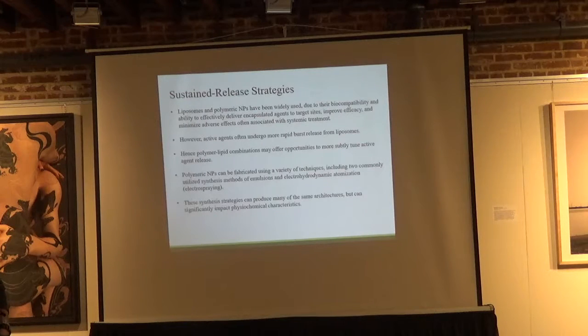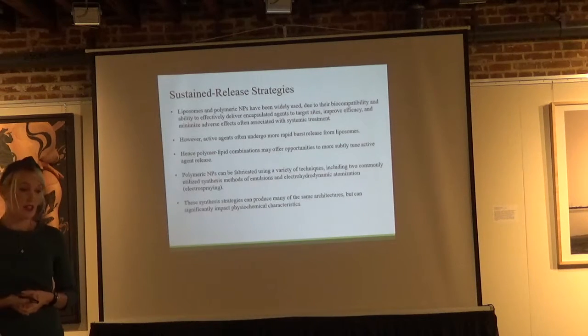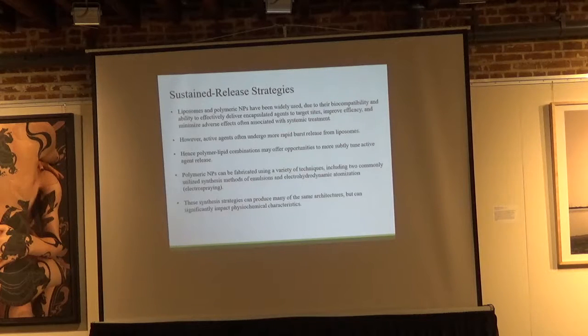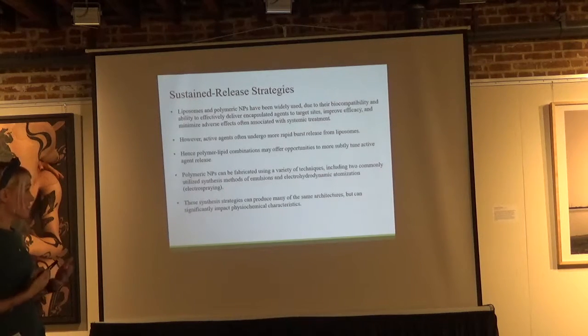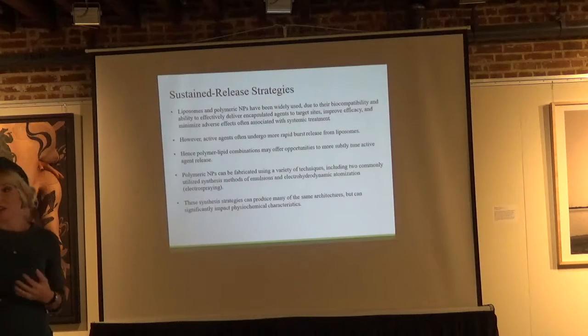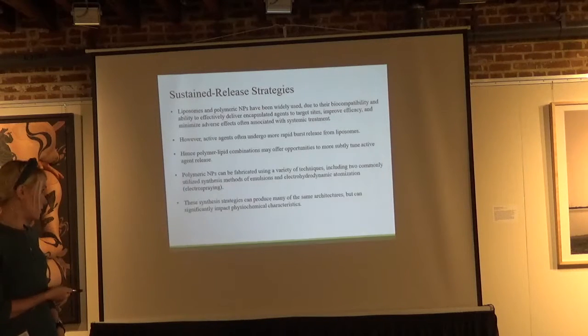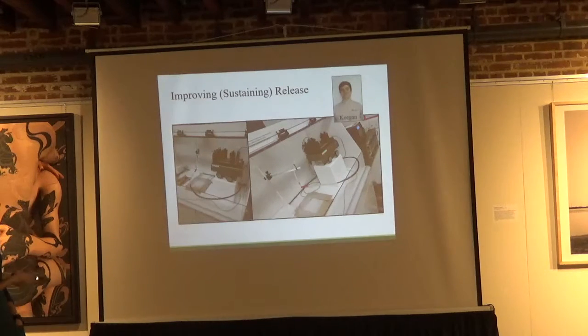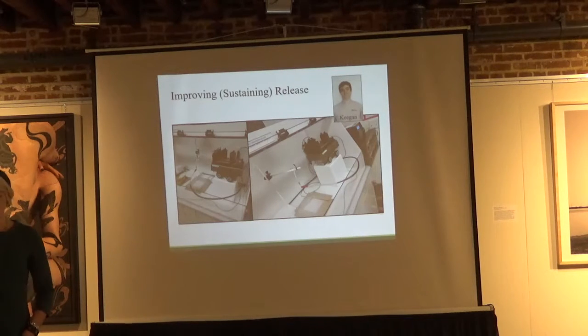However, active agents often undergo, as I showed in those plots, more rapid burst release, and in particular for lipids, it's often even worse. So the thought is that polymer-lipid combinations may offer opportunities to more subtly tune active agent release. And we can fabricate polymeric nanoparticles with a variety of techniques, but the ones that we have going in our lab are emulsion-based and electrohydrodynamic atomization, which is also called electrospraying. And so we're hoping that these synthesis strategies can produce some complex architectures of which we're looking at, or began to look at in this work. And so thanks to my student Keegan, who actually worked on this the past summer and he transformed our electrospun fiber spraying system into one that's more compatible for the spraying of particles.